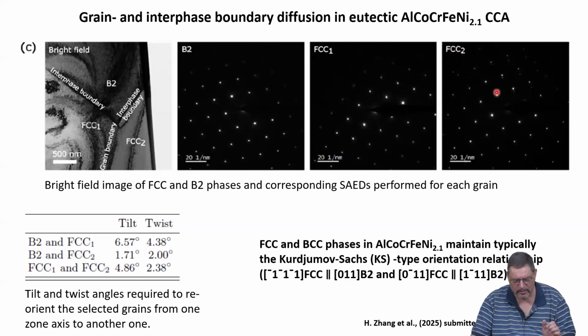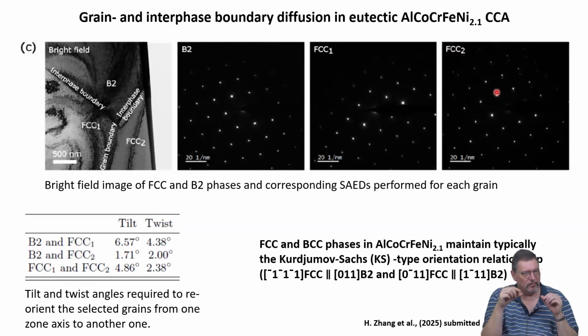Okay, good. So it's what you get, but we also see sometimes Nishiyama-Wassermann for some minor fractions also being there. And this is very important because we have some interfaces between two different phases which show this orientation relationship, sometimes also with some deviations of the ideal orientations, but still fulfilling. So we have coherent interfaces, at least semi-coherent interfaces, and we have non-orientation relationship interphases. So the same two phases come together, but the interface doesn't fulfill an orientation relationship. That means it's not a semi-coherent interface, it's more like a random high-angle grain boundary, but between two different phases.